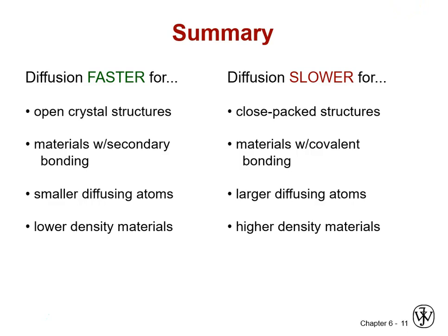So some rules of thumb for diffusion rates. Diffusion will always be faster when we have a more open structure. So for crystals, open structures are crystals with lower atomic packing factors, more open space. So BCC should be faster than FCC or HCP. Likewise, grain boundaries are going to be much, much faster than the centers of grains because, because of that mismatch that we discussed in our defects chapter, there is more open volume around the atoms. So there's literally more space for things to diffuse.